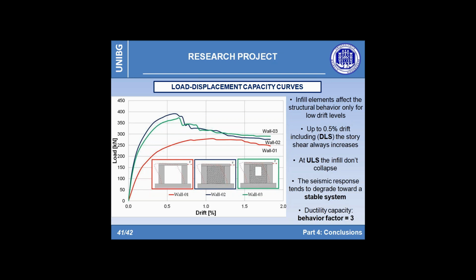Even at the ultimate limit state, the infill panels do not seem to have suffered deformation such as to cause their collapse. The welded wire mesh, despite not being superimposed in the central part of the infills, has been able to retain the connection between the main structural elements and the concrete infill slab, preventing its expulsion. The out-of-plane mechanism shown by the two halves of each infill panel has appeared to be limited and not such as to affect the stability of the external lining layers. In fact, the EPS insulation panels appear still globally intact and not detached from the structure.